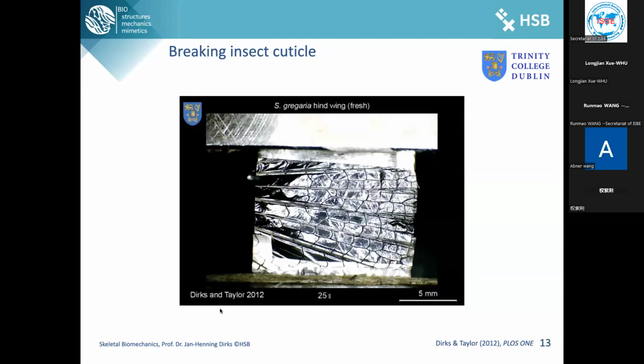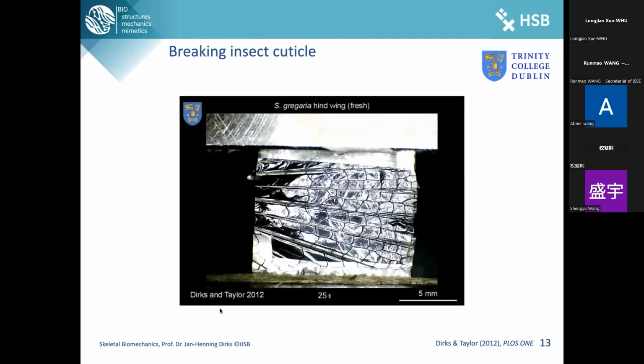And we first of all started with measuring fracture toughness. We were lucky that we were the first ones to actually determine the fracture toughness of the tibia. There was a value that was not known so far. We placed incisions into the legs and so on. And we found that cuticle has an extremely high fracture toughness, meaning resistance to crack propagation. It's very good in resisting crack propagation. It's very difficult to drive a crack through many parts of the insect exoskeleton.